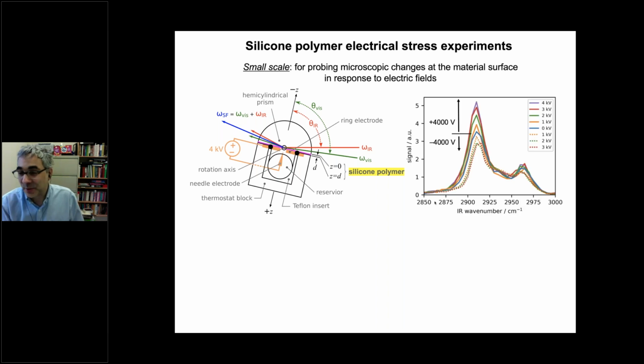And the preliminary results are really interesting. What they show is that we can see that the surface hydrophobic groups, these methyls, which are important for imparting hydrophobicity to the silicone rubbers, are changing in response to the applied field. And they are also affected by the polarity of the field. So you can imagine that if you have an AC field here, these methyls are flipping back and forth from the surface very rapidly. So one of the ways we used to think about loss of hydrophobicity of these materials is that the methyls are changing their orientation over time and are not being able to stick up as much as they used to be when the material is pristine.